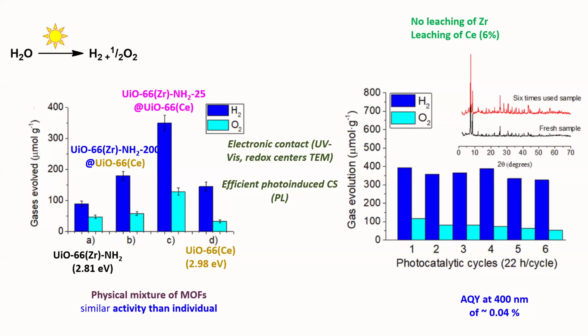And one of the important experiments was when we checked the physical mix of these 2 MOFs. So for these samples, except these 2, B and C correspond to the core shell type. But if you just take this UiO-66 zirconium amino and UiO-66 cerium, these 2 solids, and physically mix them, instead of making a core shell, and perform the reaction, the activity was almost similar to this. So there was not much improvement, and this was one of the important control experiments to make sure that we have generated core shell type MOF-on-MOF solid instead of just a physical mixture, and the activity was superior in this case, which reinforces our characterization results.